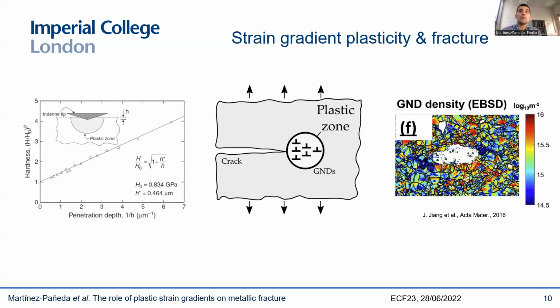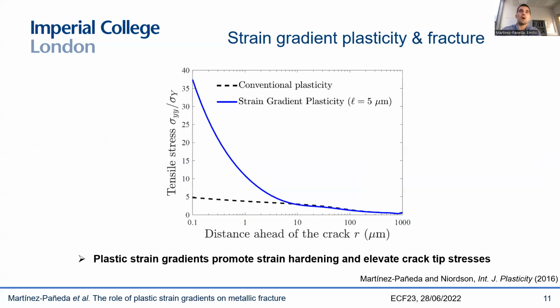And in fact, if you take one of those strain gradient plasticity models and decide to simulate the stresses ahead of your crack, you see what you see in the slide. So this is the tensile stress ahead of the crack. So the crack will be here, and this is the distance ahead of the crack in micrometers. And this is a simulation run with a strain gradient plasticity model. And in the dashed line, you see the result predicted with conventional plasticity.